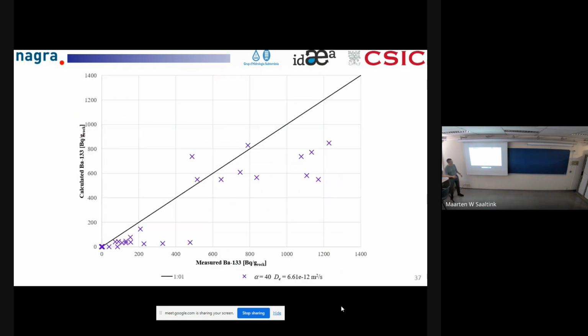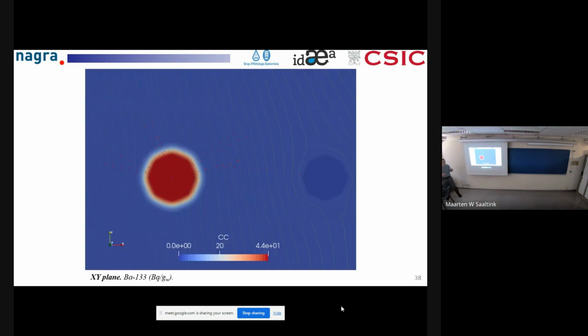And again, here is the match between calculated and measured values. We also see some large values up here on the right, but we have a relatively decent match between calculated and measured concentrations. And again, this is the calculated tracer plume, which is an even narrower zone around the injection.